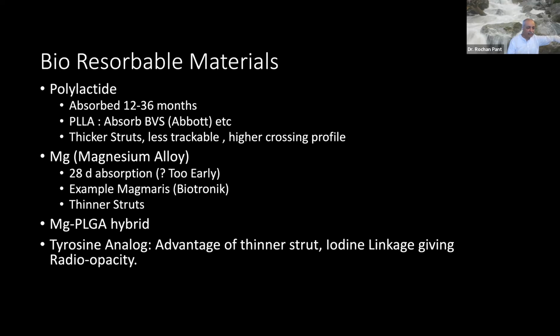So they came up with the other material, which was basically polylactide, PLLA, which was used to make resorbable sutures earlier also, which gets absorbed over 12 to 36 months. There are lots of variants of this basic polymer. The problem with this has been that to get the same radial strength, hoop strength, etc., and radio opacity, you need to have thicker struts. So it tended to be rigid. Everybody who used the coronary absorbable scaffold stent complained about the rigidity of the stent and difficulty of taking it to the right place because of the higher crossing profile.